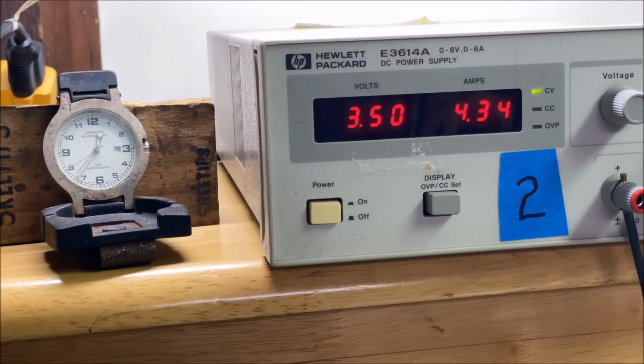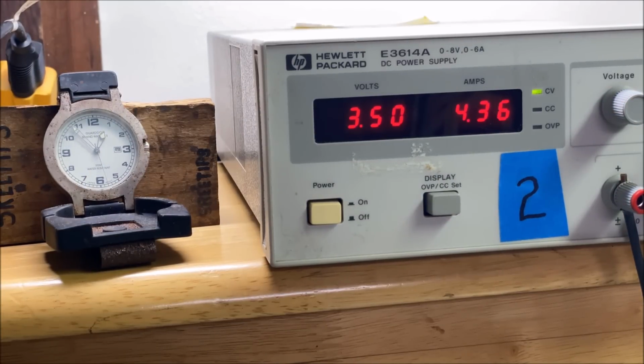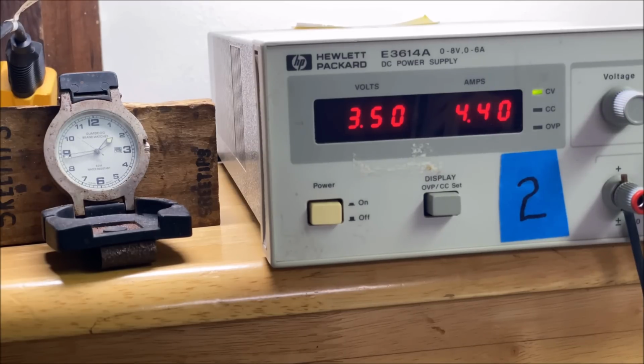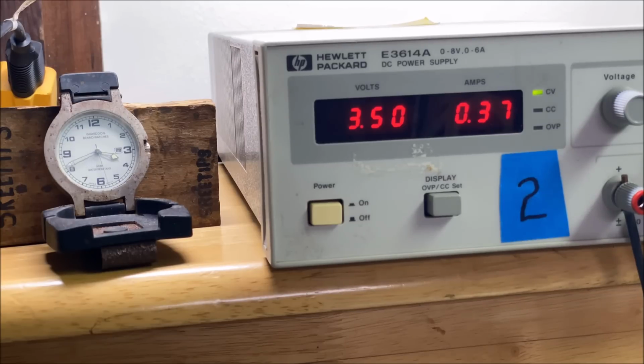Here you can see the current flow stays up around 4.3, 4.4 amps for quite some time, and then it slowly begins to drop off as the silver gets dissolved in the bottom of that anode filter, and boom, all of a sudden, once it's gone. And then after that, it becomes very erratic, going up and down on the current flow.